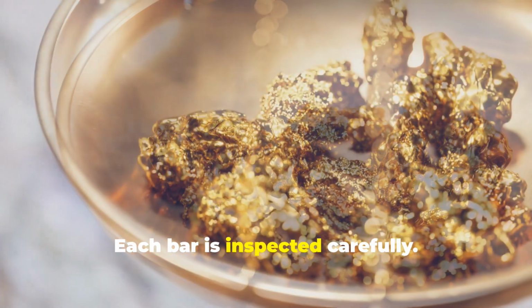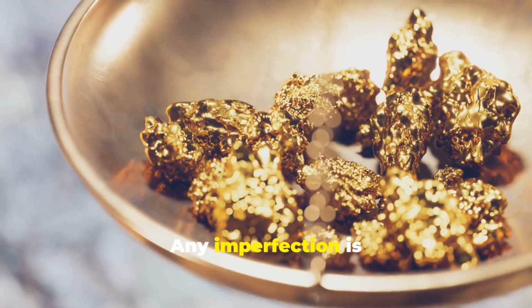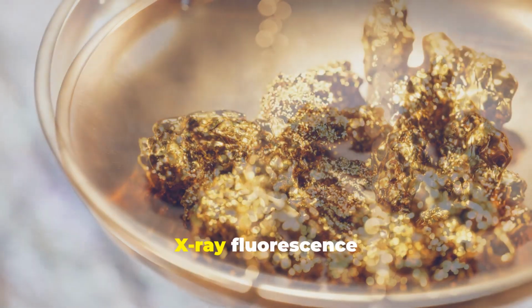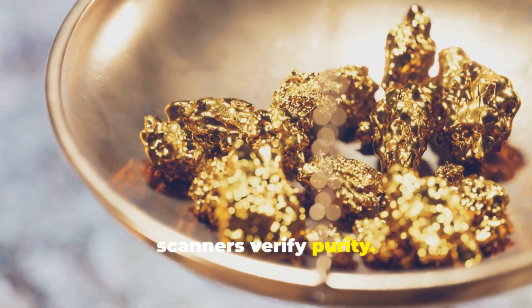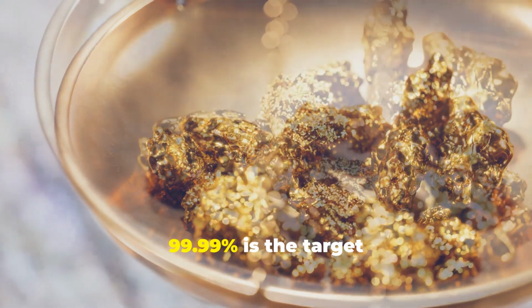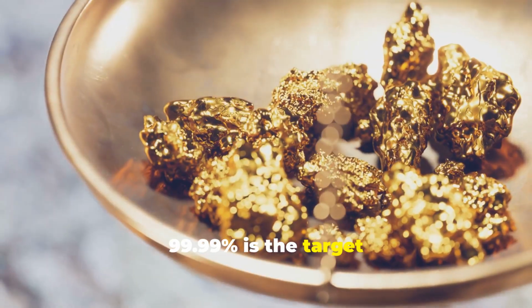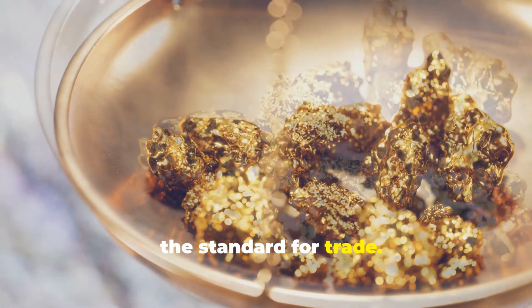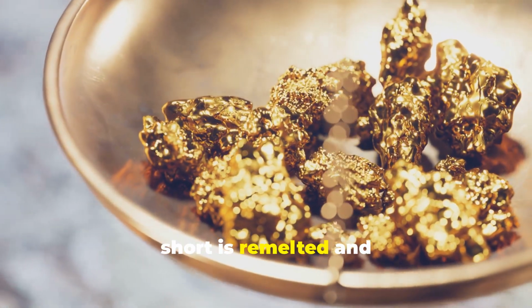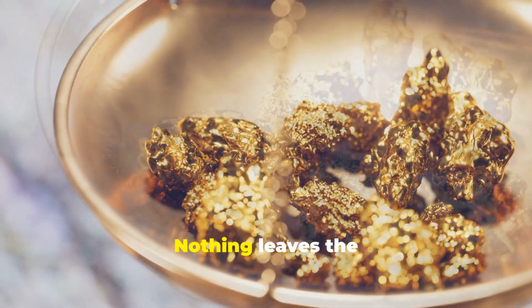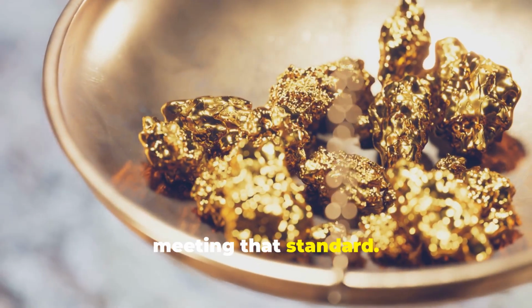Each bar is inspected carefully. Any imperfection is corrected immediately. X-ray fluorescence scanners verify purity. 99.99% is the target, the standard for trade. A single bar falling short is remelted and refined again. Nothing leaves the refinery without meeting that standard.